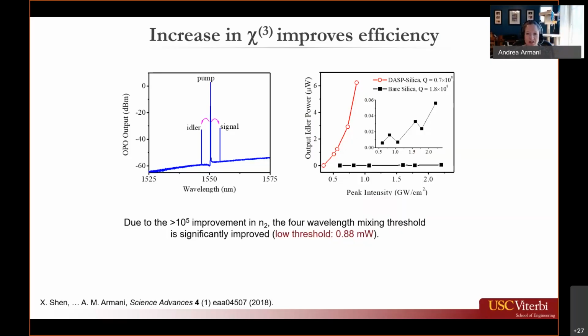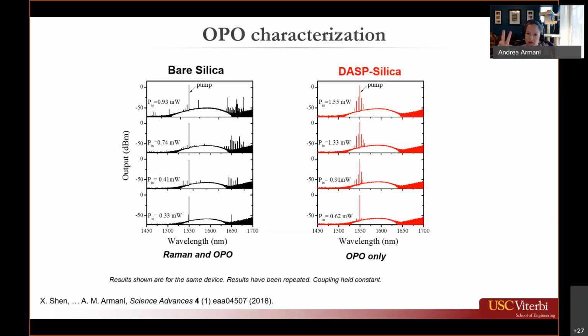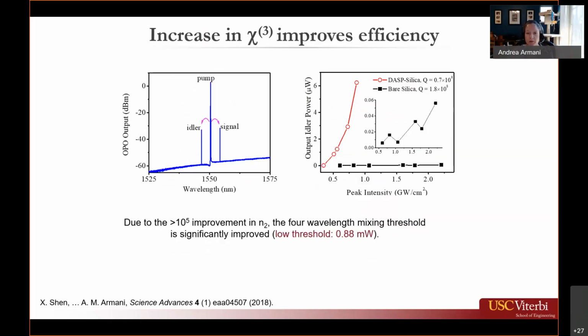What was interesting in this project is our initial goal was to try to create very large frequency combs. But in the end, because our dispersion changed, we ended up making combs, you could call them combs, that looked like this. They quenched very quickly because our dispersion changed very quickly. So this made a device that was very effective at making photon pairs at very low input powers, but really only made single photon pairs, right? It was unable to make large combs. Importantly, it was able to make photon pairs that had fairly large spectral separation. And making photon pairs is also an area of interest of a lot of researchers, more fundamental physics researchers.